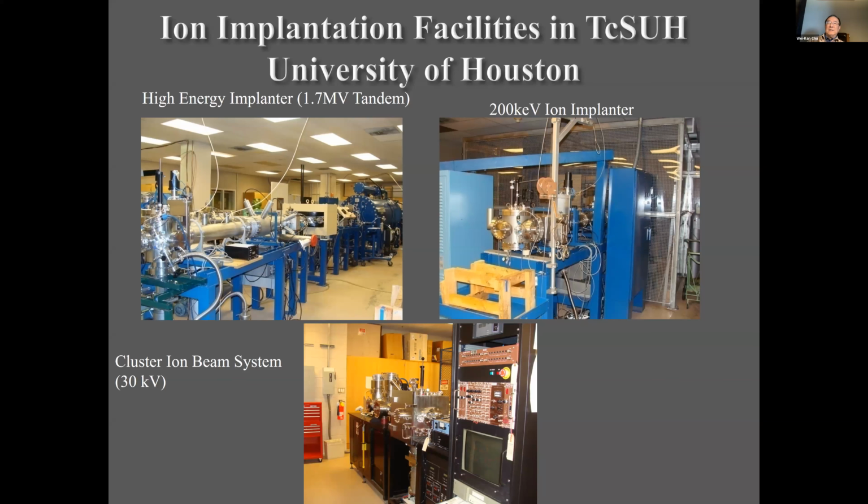You spread the argon into the vacuum, then the argon immediately freezes into small droplets. The droplets have a size of a few hundred to a few thousand atoms. Then you spread some electrons on top, so those droplets become charged particles. Now you put in 30 keV, and they start accelerating.